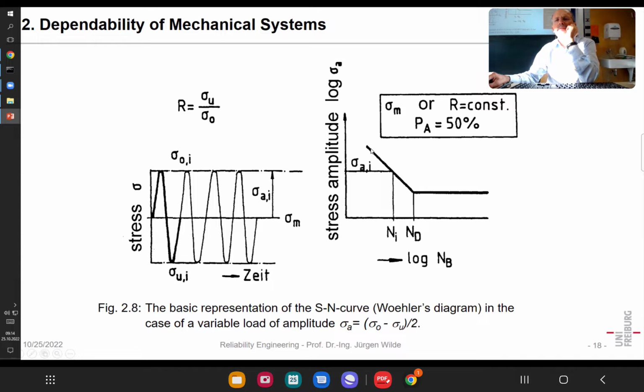That curve has, of course, much scatter, you will see. And it has a slope going down. That clearly means lower stress level, higher number of cycles. And you also should say that's not the number of cycles, but the logarithm of the number of cycles. And here you could say that N_D is somewhere 1 million to 10 million cycles. Yeah.